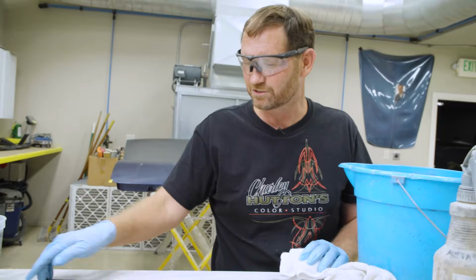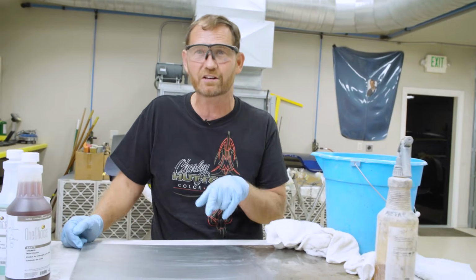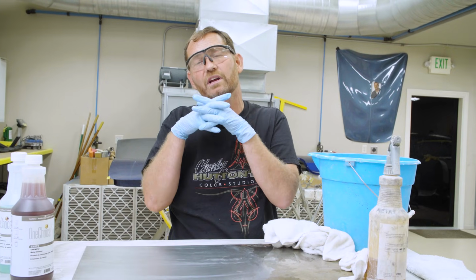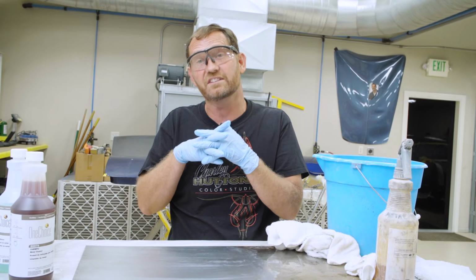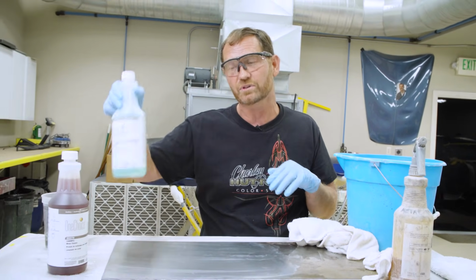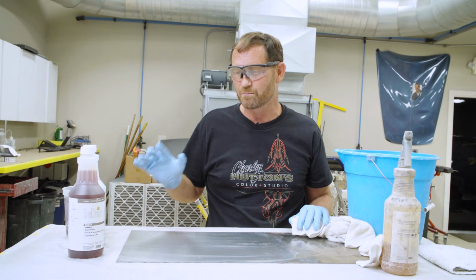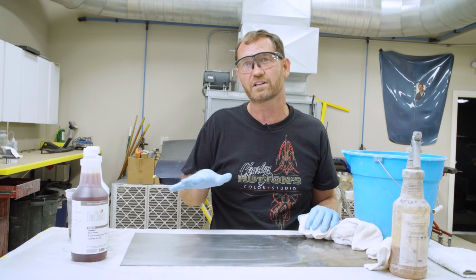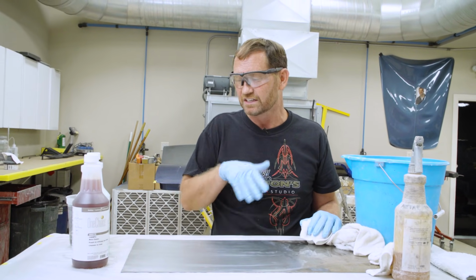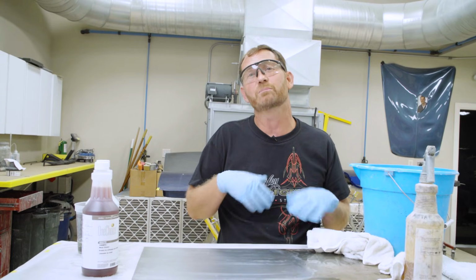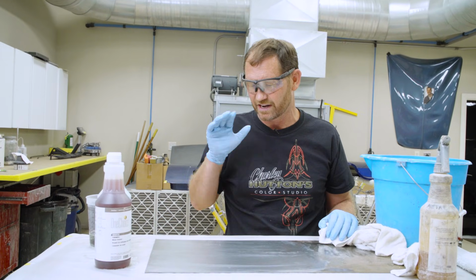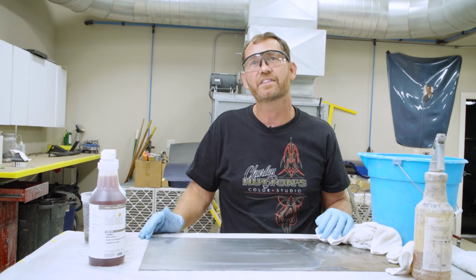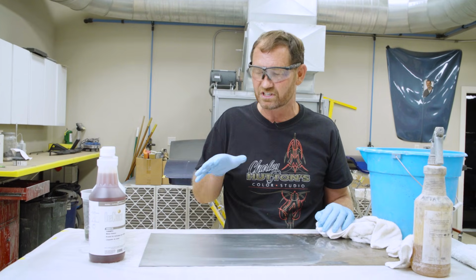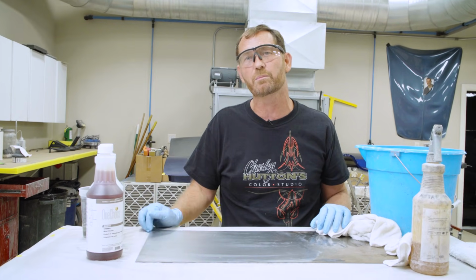So now this panel is prepped, and now if you were to look at this under a microscope, you'd see that crystallized coating on top, which is going to be the zinc phosphate because we finished it off with the 520. This is the best process to use on bare metal, because now when you put an epoxy sealer over top of this and then begin your body working process, you've created a great corrosion barrier. Now you know that anything that you put on top will stick. It's not gonna peel from the bare metal.